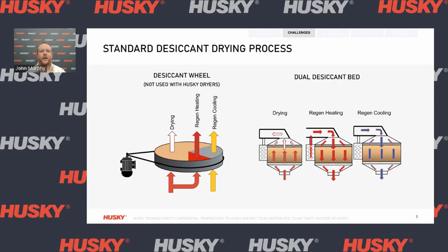For dual desiccant bed technology, the air flows through one tower containing desiccant material, while the other tower goes through a humidity-reducing regeneration process. As air flows through the desiccant tower, moisture is removed from the air and absorbed by molecular sieves. Once the tower has saturated with water, a valving mechanism switches to the other tower to create a continuous process. Both of these technologies have been in the industry for many, many years and are effective when drying virgin PET material.